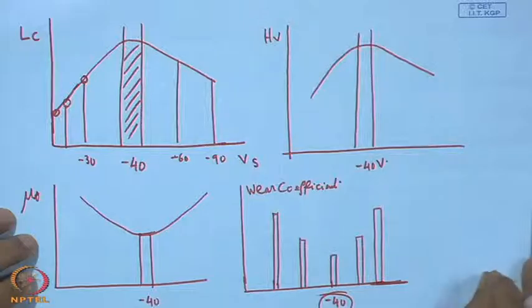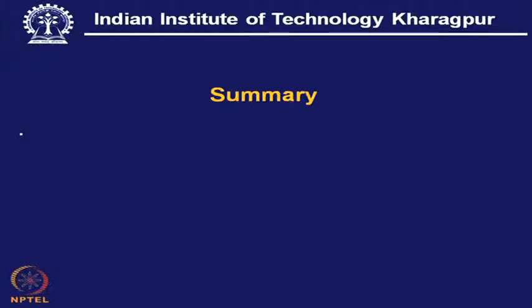So, what we can summarize is that we have examined various types of coating architecture. One may be just molybdenum disulfide. However, it is known that molybdenum disulfide alone cannot work so effectively for all practical purposes in normal atmosphere, and that is why molybdenum disulfide always comes with material like titanium, chromium and similar transition group materials to improve its property, that means protecting against moisture, oxidation and holding that basal plane, that means this 002 plane, parallel to the substrate surface.